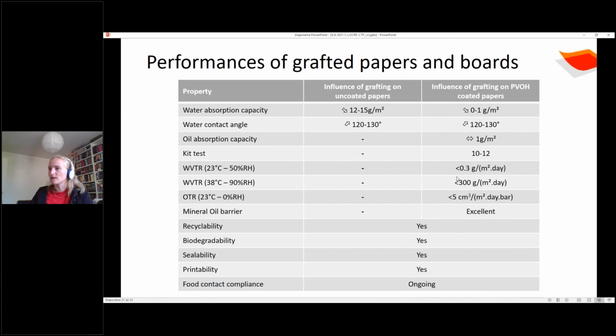And we get actually at 23 degrees and 50% relative humidity, quite good water vapor barrier, which unfortunately is not that good in tropical conditions. So these are things that should still be improved. And this material, thanks to the polyvinyl alcohol layer, is also an excellent barrier to oxygen and mineral oil. And as I mentioned earlier, this does not change the recyclability, biodegradability, sealability, printability of the paper substrate. Food contact compliance is ongoing. So we are investigating this.